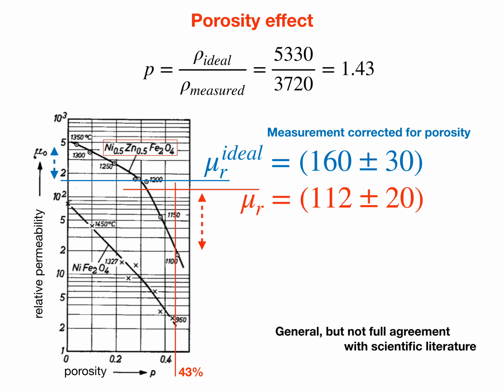Furthermore, there could be impurities at grain boundaries. The diagram also shows that the permeability of the material depends strongly on stoichiometry. Replacing the zinc with nickel gives a much reduced relative permeability. It is clear that the permeability depends on the material and its properties, and also its synthesis in a complex fashion.